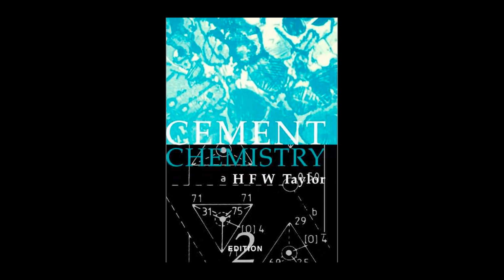At very low dosages, these molecules adsorb onto the surfaces of the newly forming hydration products, especially the crystalline calcium hydroxide and the CSH. And what does that do? By forming a complex or a thin film, they effectively poison the nucleation sites. They physically interfere with the ability of the crystals to grow and link up, and that's what extends the induction and the setting period.